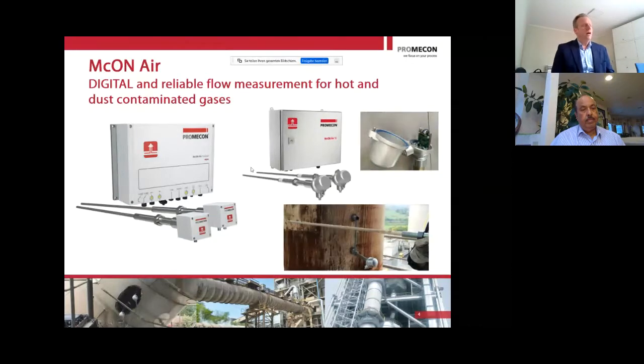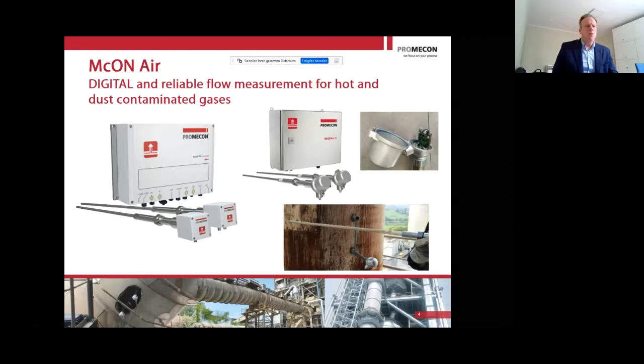Here you can see basically our system. Our measurement system is different from the traditional way of measurement. The traditional way of measurement is usually measuring the delta pressure over a certain flow resistance. So you have a venturi or you have an airfoil and you measure the delta pressure. When you have a lot of dust, this is very, very difficult because your pressure taps keep on clogging. You can see in the lower right picture, we have pulled a sensor out of a downcomer duct, and you can see how much dust is lying on the surface of that sensor.